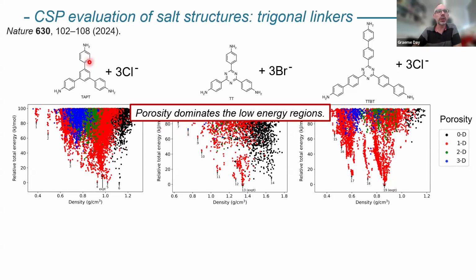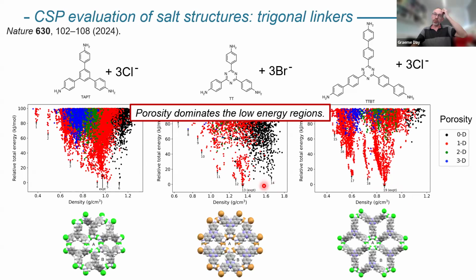But if we look at some of the other linkers, here it's these trigonal linkers here, where we have these amines on the corners with either chlorides or bromides. Now, these are the CSP landscapes. And red are porous structures with 1D porosity, so they have channels in those structures. What you see now is that all of the low energy regions of these landscapes are porous. So this design of stronger electrostatics into the material seems to have worked in that it stabilized porous structures. And if you look at these starred structures here, which are the global minima, and in this case, not quite the global minimum, but close to it, those are the observed structures that we get when we make those in the lab. So again, the CSP process has told us which of these combinations is going to work. We've got to that by learning from landscapes of previous studies.